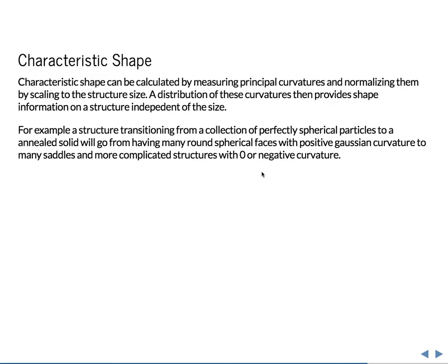One of the things to be very aware of is that when you do these normalizations, you have to be very careful about discretization problems. If you have a shape that's 1 pixel large, the thickness of this shape will be 1. The curvature will be perfectly spherical, because that's all you can be with 1 pixel. As that object grows, if it becomes 2 pixels, by definition it's now all of a sudden incredibly anisotropic. It now has very many different curvatures.